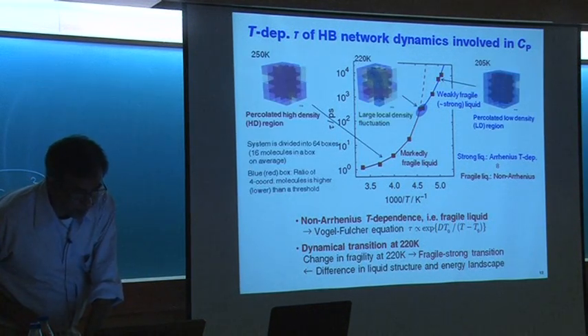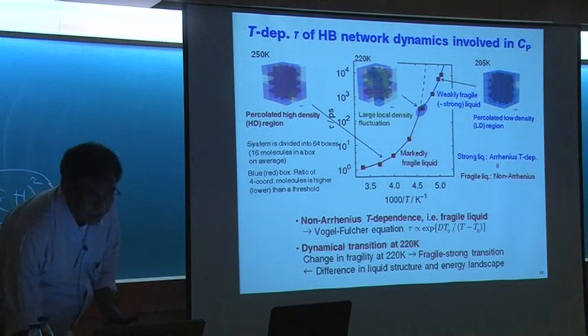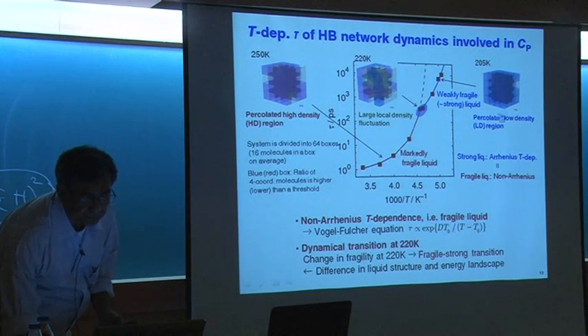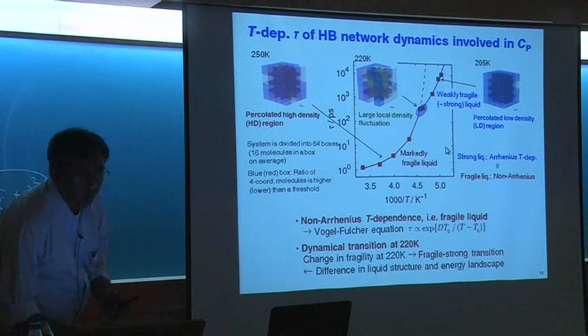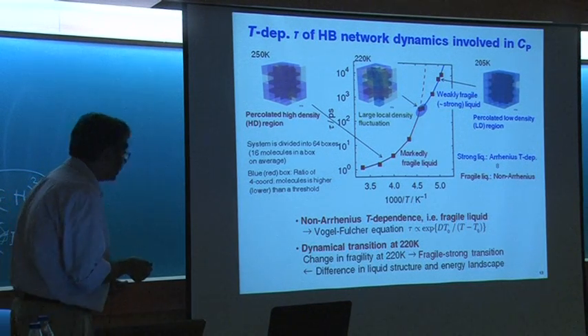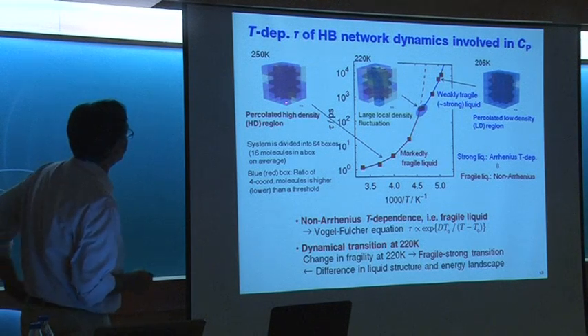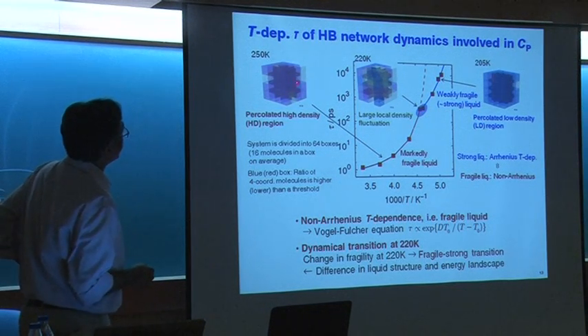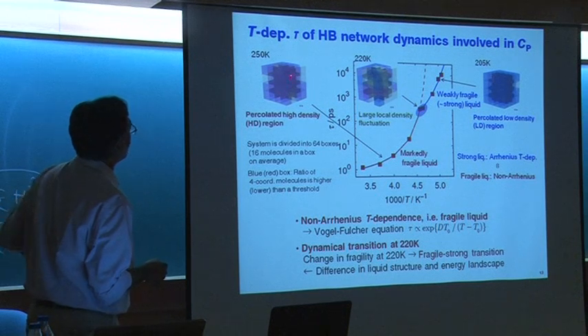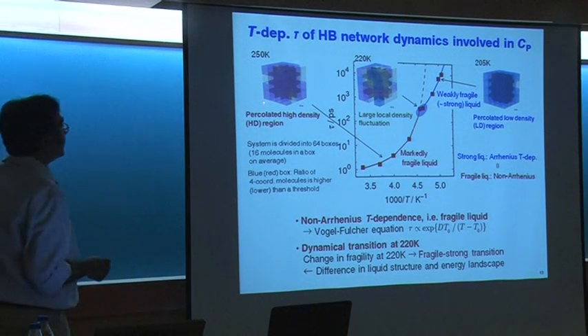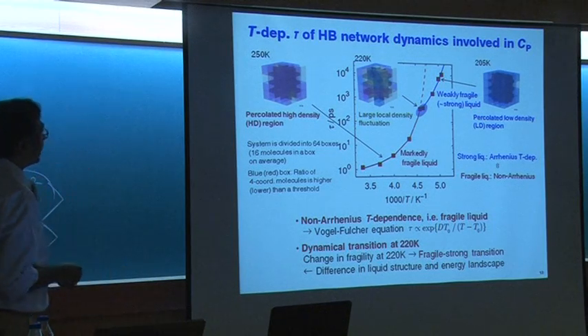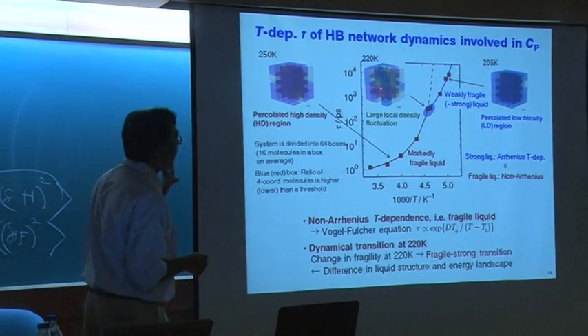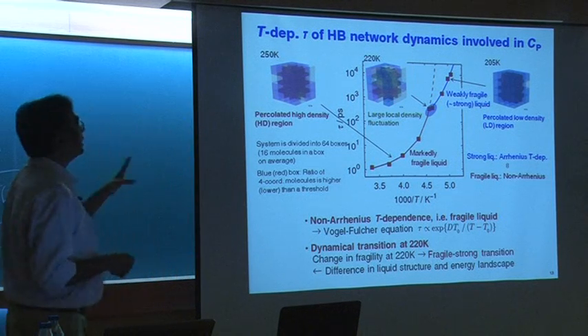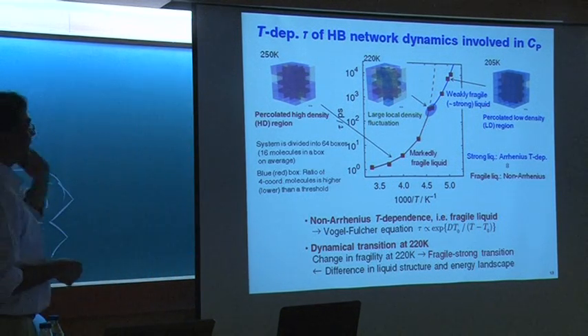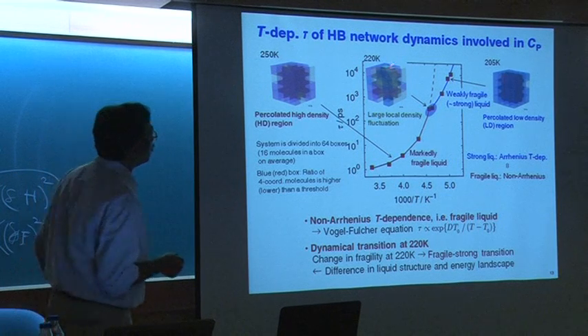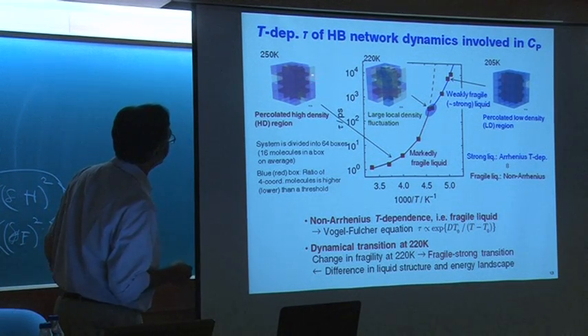A lot of work has been done on that, but there is a movie here, probably it will not work. No. Okay. That's why one should not trust one's opponent. So what is shown here, at 250 Kelvin, you are mostly in high density liquid. The normal liquid that we say is high density. That density is 1 or very close to 1. As you go to lower temperature, remember ice has a density of 0.92 on our scale of water density 1, which is the universal scale.